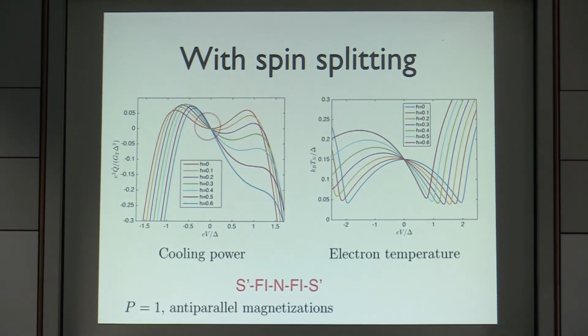And you could ask, for example, can I cool the electrons more than in the SINIS case? Unfortunately, the answer is no, not really. These are the cooling curves of the normal metal as a function of voltage. The blue curve is the case where there is no effect of magnetism, and you cannot get much better. You get the lowest temperature at a lower voltage, which translates to a better efficiency, but otherwise it doesn't matter too much.